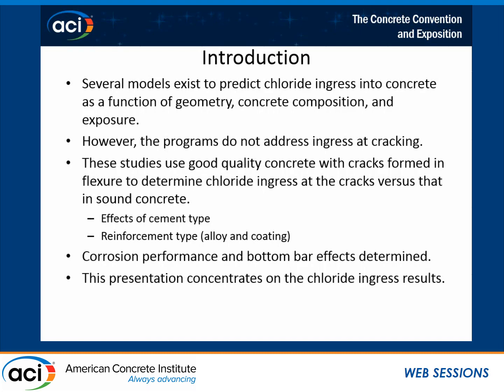or what remedial actions we have to take to eliminate the role of cracking so we can use our models. These studies, unlike a few others that have been done in the past, use very good quality concrete, and you'll get an idea of what cracks formed in flexure to determine the chloride ingress at the cracks versus in sound concrete. Mainly it was done for corrosion testing, and with the type of flexural crack we make, we have extremely large cathode to anode ratios. I'll show you the samples in a little bit. But we can study the chloride coming through the crack to see what the effect is versus the sound concrete, and that's what we're going to look at.